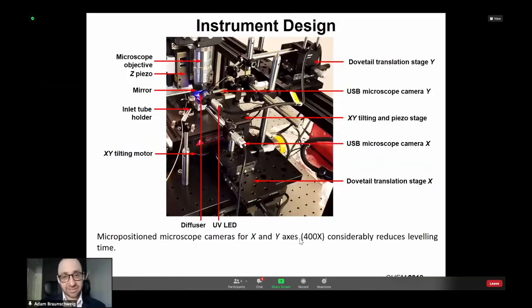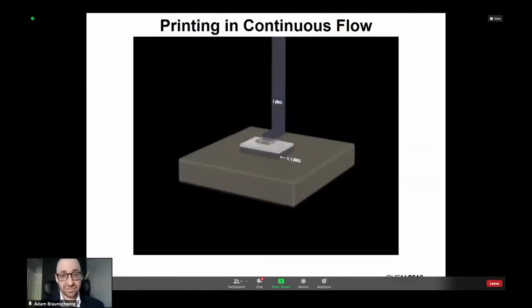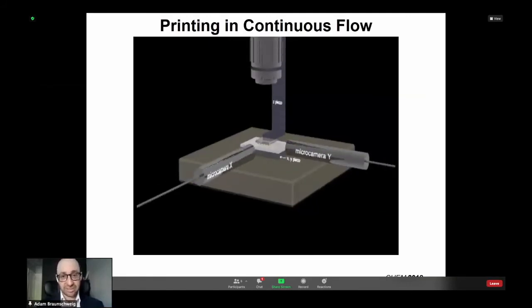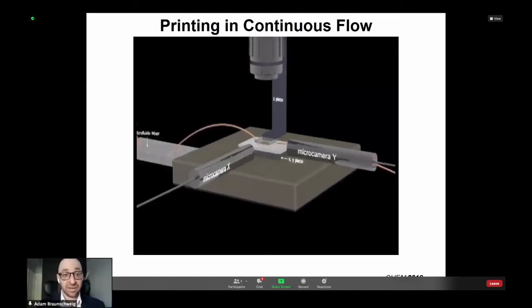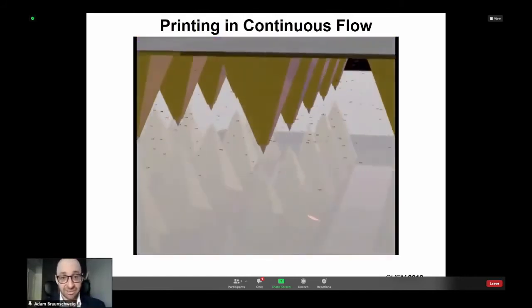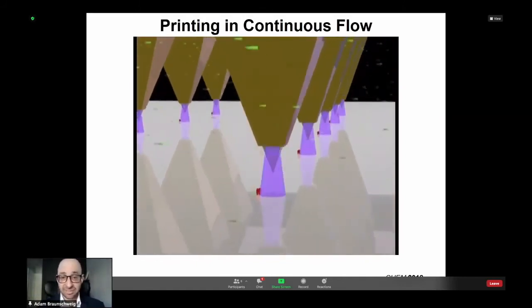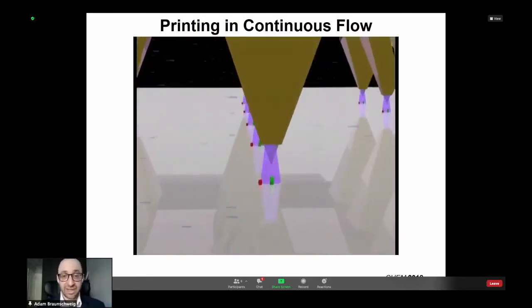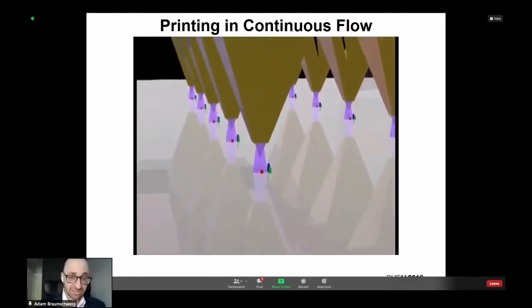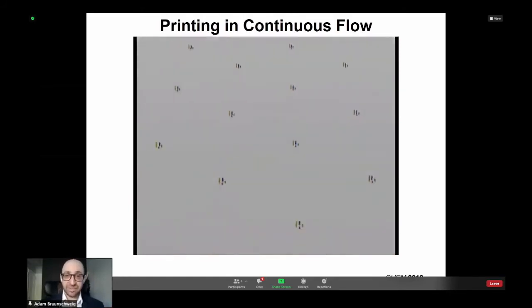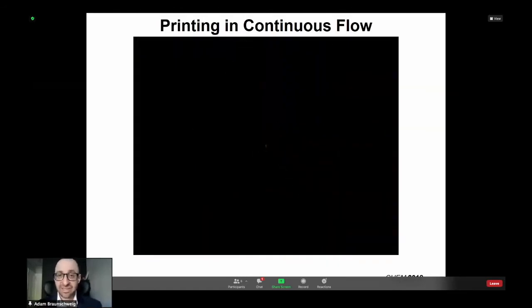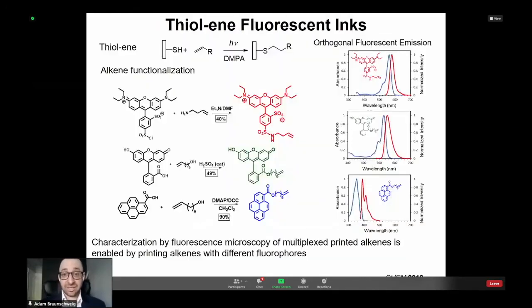This is what the instrument looks like, but I don't find this picture particularly useful. So we made this cartoon that illustrates how our new printer works. So you have the microfluidics. We have some cameras to monitor what's going on underneath. Then you have these tips, and then you can apply some stimulus, either light or force, to drive reactions on the surface. And here what we're doing, what these different colors show, is either different chemicals under the tip or different conditions. And we're doing this all under the same surface, repeating this experiment thousands of times so we can do statistically significant data sets all in a single print.